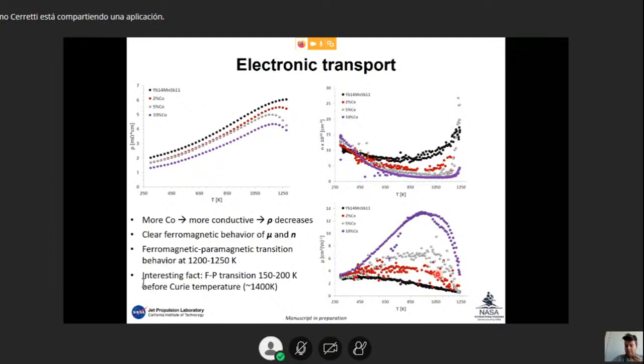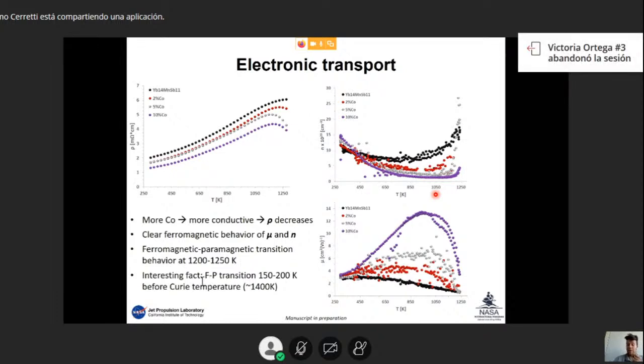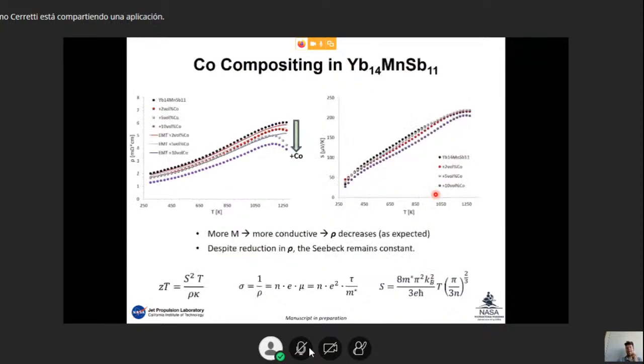So this, let's say, reverse U shape of the charge carrier mobility is a very characteristic behavior for this transition for a ferromagnetic material. But still, we were surprised that this transition occurred 200 degrees before what should have happened. And what we explain is that probably, due to the tiny sizes of the inclusions and the fact that the concentration is so low, the cobalt inclusions act as single and dispersed, really remote, so they do not communicate with each other from a magnetic point of view, and that reduces the Curie temperature, the magnetic transition temperature, for the material.